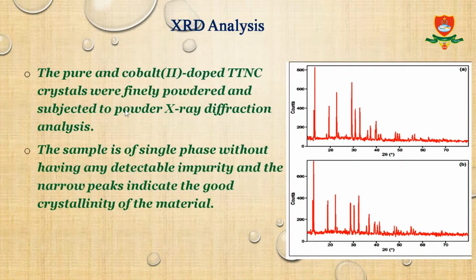XRD analysis. The pure and cobalt-2 doped TTNC crystals were finely powdered and subjected to powder X-ray diffraction analysis. The sample is of single phase without any detectable impurity, and the narrow peaks indicate the good crystallinity of the material.